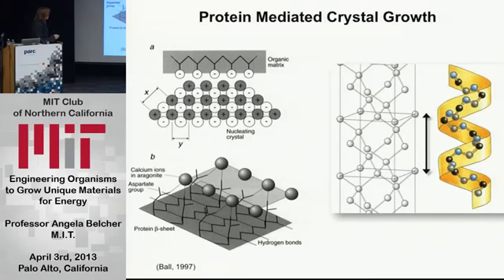And the way that this works is you have what I call an organic matrix, but it's actually, in this case, a protein. And the protein, if you go back and you think about those amino acid functional groups that are linked together, in this case, these are negative charged amino acids, and the negative charged amino acids, in this case, aspartic acid, glutamic acid, can grab onto calcium, put down calcium carbonate, start to nucleate and grow the structure.